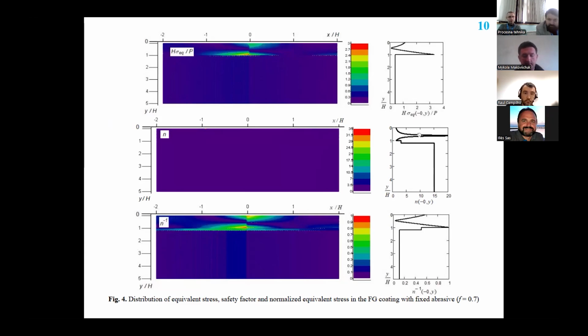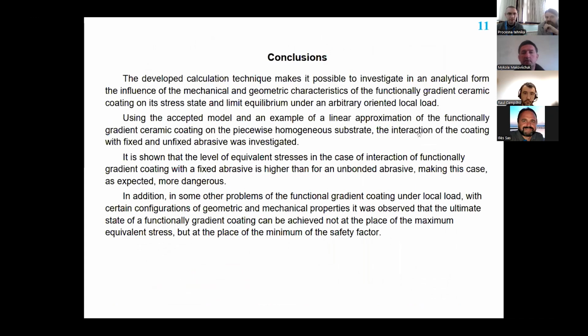Also, since we have a non-homogeneous coating, we should also take into account the spatial distribution of strength characteristics, in this case the value of the yield limit of each layer. Therefore, a more correct determination of the limit state of layered coating is given by the distribution of safety factor or normalized equivalent stress. So let me read the conclusions. The developed calculation technique makes it possible to investigate in analytic form the influence of mechanical and geometric characteristics of the functional gradient coating on its stress state and limit equilibrium under an arbitrarily oriented local load.